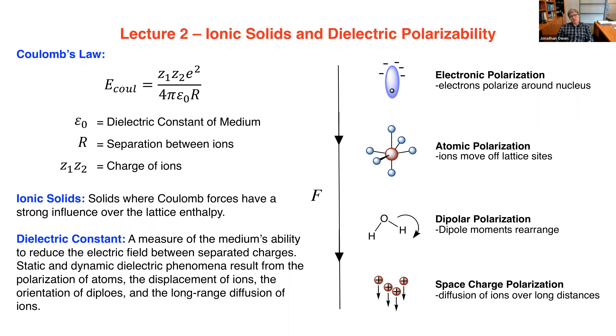There's also atomic polarization, where atoms in the crystal move but don't actually flow — they move off of their preferred crystallographic positions. The lead halide perovskites are famous for having very high polarizability. A lot of it has to do with the motion of the lead atom within the halide octahedron. That motion of the lead atom contributes atomic polarization to the dielectric properties of lead halide perovskites.